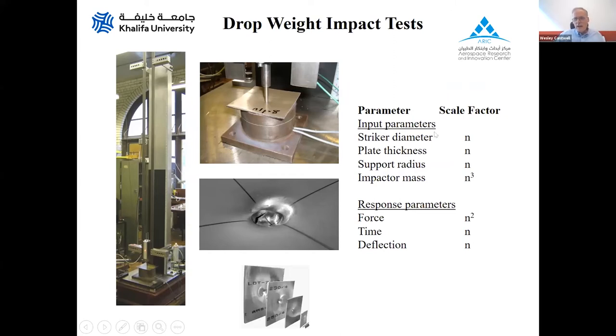I mentioned the scale factors earlier and we can identify them. The scale factors for things like striker diameter, plate thickness, and the support radius are fairly straightforward. So they need to scale with the scale size. So you need four scale sizes of circular supports and strikers, et cetera. The impact mass now should scale as N cubed. And that's where your impact masses rapidly escalate out of all proportion. Because if you're using 1 kilogram on your N equals quarter plate, you need 64 kilograms to test your largest plate. So things become rather challenging.